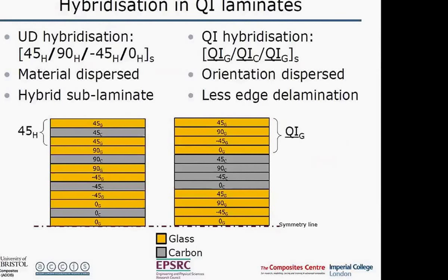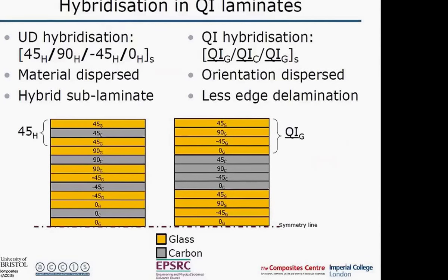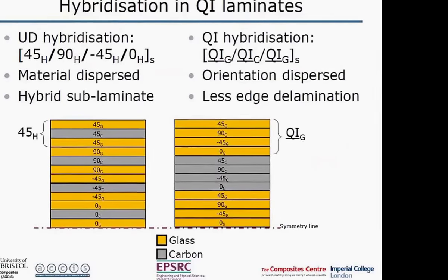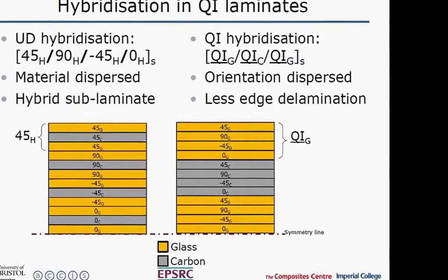The alternative way of doing it is instead of dispersing material, disperse the orientation. So in this case, we've got a block of quasi-isotropic glass, a block of quasi-isotropic carbon, another block of quasi-isotropic glass. So there's plusses and minuses of these different approaches. One of the things about this one is delamination, because you're mixing orientation. Here we're mixing different materials. Here we're mixing different orientations, and that gives us a bit less susceptibility to edge delamination. So we've looked at both of these, and they have plusses and minuses. But I'm going to show you some results now from this configuration.